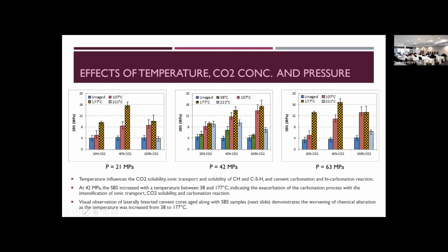And if you look at the data here, for example, high pressure doesn't really improve the bonding at all, which means that, as the ANOVA was telling us, pressure is the least significant parameter in this process. I fully agree that a non-parametric study will be important, and our laboratory right now is trying to expand the testing. We are varying sizes now from as low as 1/2 inch to almost 4.5 inches for the cement. And we are trying now to see whether the geometry itself plays a role and whether that geometry change can be at least scientifically explained.